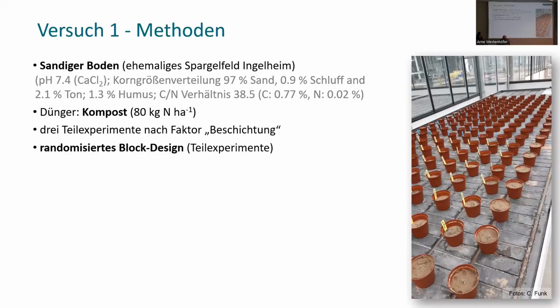We carried it out in a greenhouse, and I used a sandy soil. 97% is really sand, low humus content of 1.3%. A fertilizer, to have something organic in there, I used compost, 80 kilo nitrogen per hectare. As it was quite an extensive trial and I needed to handle many things, we had three sub-experiments along the coating factor. I'm going to speak about that in a moment.